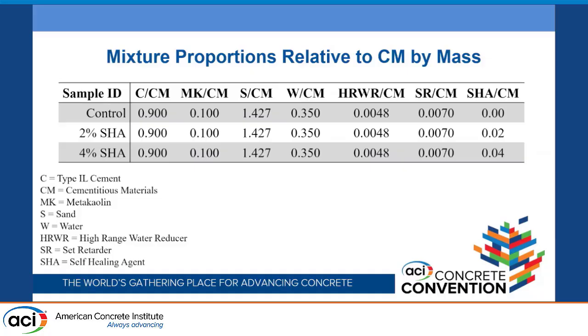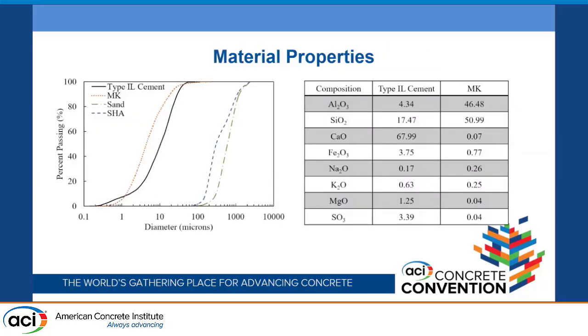And then we modified that mixture portion using a 2 and 4% addition of our bacterial-based self-healing agent, which we received from Basilisk. And from that, we did some basic material properties testing just to give it a little more additional background.